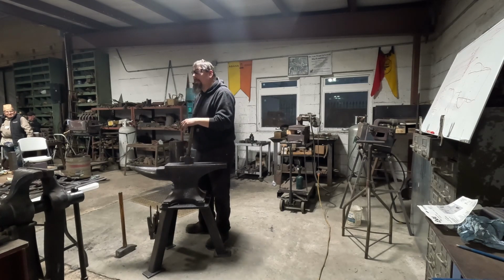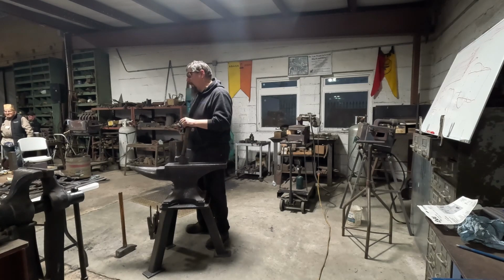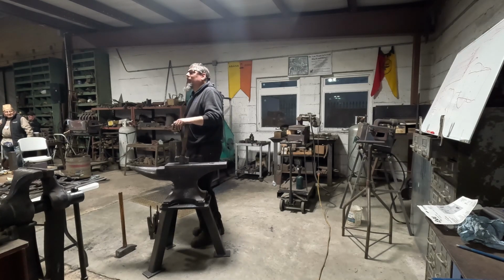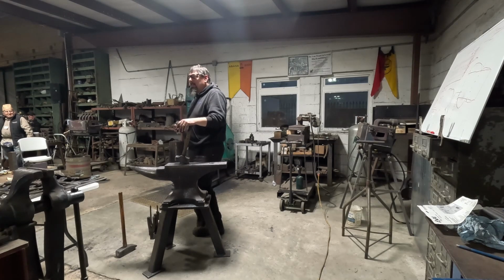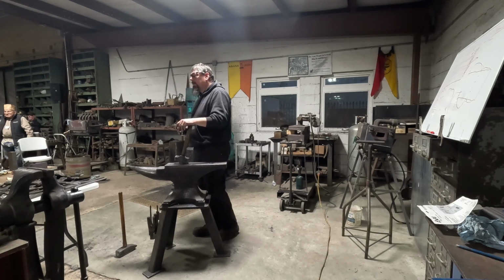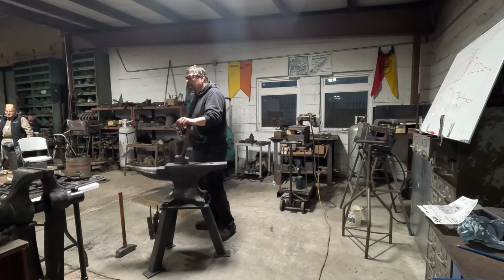So that's the only time I have ever personally encountered that problem, because we don't make steel like that today. We put manganese in there to deal with sulfur, and today in modern steelmaking practice, you can get sulfur out if you want to, and so that's rarely a problem. But you start to see in the literature in the very early 1900s where they recognize that problem. They actually recognized the problem earlier than that, but you start to see published values of what the proportion should be for manganese and sulfur in the early 1900s, like around 1910.